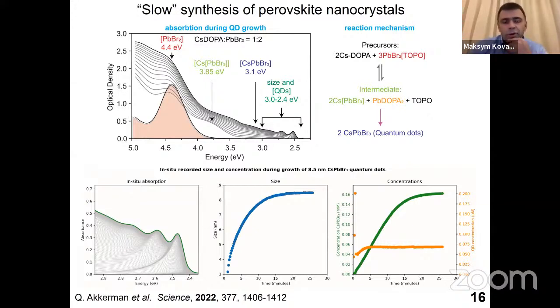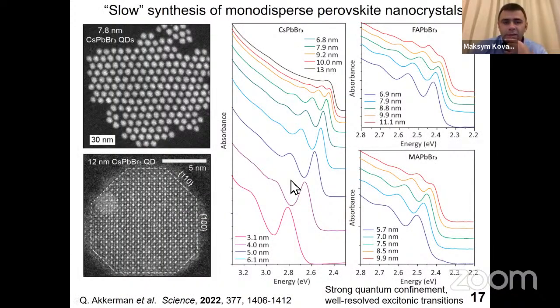this synthesis is so much more convenient and better controlled that we now entirely shift to this approach. One of the reasons why this synthesis is beneficial is that you can also expand it to hybrid perovskites, which have been traditionally very difficult to produce because they are much more fragile. Now we can produce formamidinium lead bromide or methylammonium lead bromide with the same degree of size control, down to very small sizes. So with this new synthesis, you can isolate extremely small nanocrystals, down to 3 nanometers, in a large quantity and with retention of stability throughout the purification.